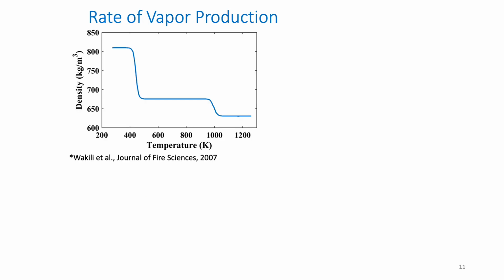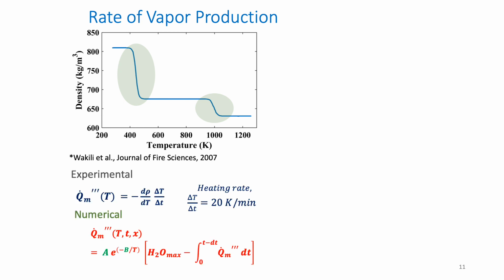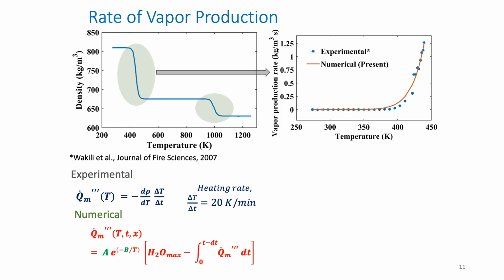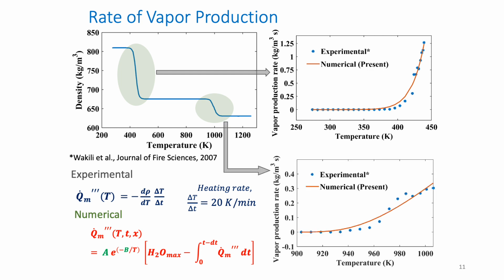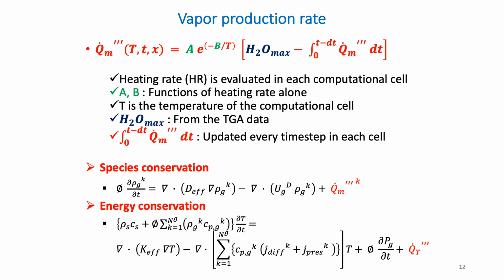So for that, initially we looked at from the literature some TGA data at a constant heating rate, and we converted that from a function of temperature to a function of time, and we developed Arrhenius type numerical equations as a function of two Arrhenius coefficients A and B and remaining water content in the gypsum board and temperature. We compared that for two stages of the gypsum calcination, and we continued that analysis with our own TGA measurements.